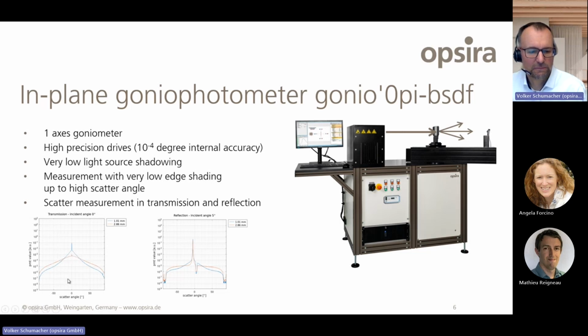This is reflection, and this is transmission, and here we see the reflection. And sure, for the reflection, we have a very high specular peak from the surface, from the polished surface, and then we see the reflected scattered light for the 2 thicknesses.